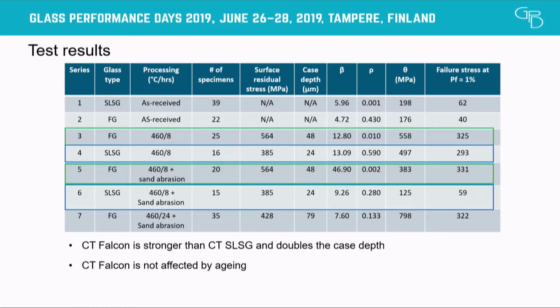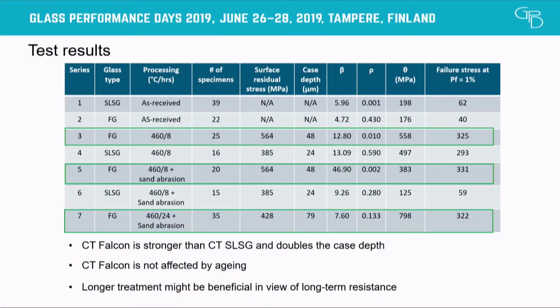So for me, these results mean that the chemical tempering and the values of the case depth and the surface residual stress are very crucial. Another important remark is that if we consider a processing time of 24 hours, the case depth goes up to 79 microns, so it's even more important.